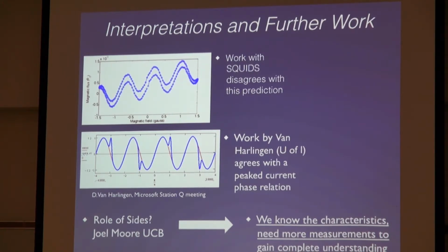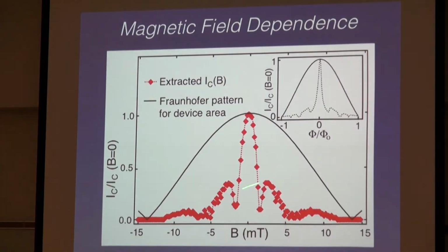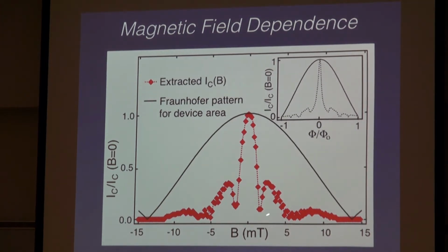So to get this Fraunhofer pattern, we had to propose a funky current phase relationship, and one in which at pi and 3 pi, we actually had peaks in the current phase relationship. And we can kind of emulate this property where you get a narrowing of the first central peak and an elevation of the first low or first zero. If you do that,